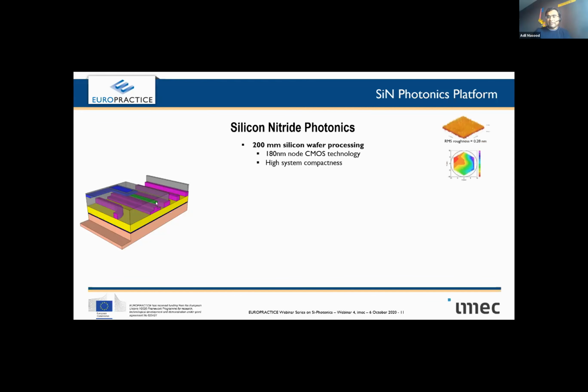So, what are the main advantages of this silicon nitride photonics on CMOS technology? It's fabricated on 200mm silicon wafer. And since we are using the nodes defined by CMOS technology, it's a 180 nanometer node CMOS technology. It's not the state of the art, but then you don't want a sub 5 nanometer waveguide where light won't even be confined. So when it comes to silicon nitride, which has mainly large footprint and features because of its relatively low refractive index, even older technology nodes can be used. So in the case of Imec, it is 180 nanometer CMOS technology. Even that gives quite high system compactness.